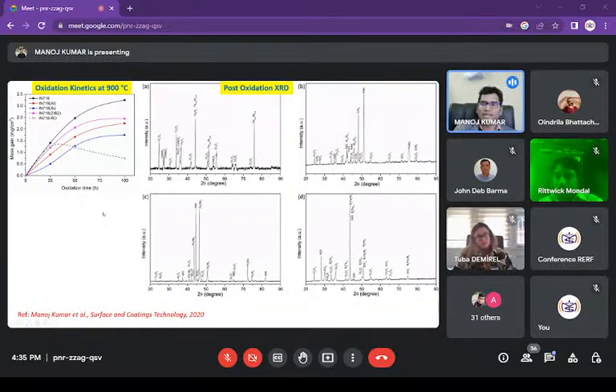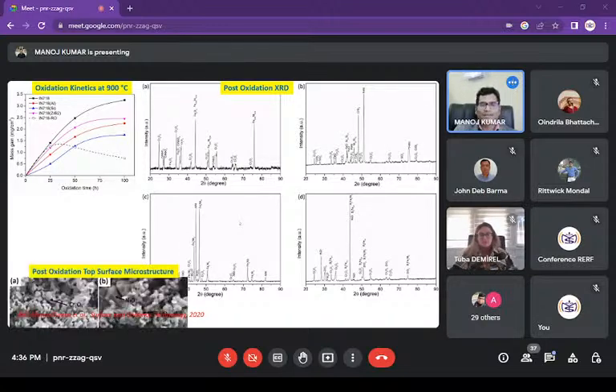And after oxidation, we took out the sample and tried to understand what phases are forming. Why the silicon alloyed surface is not getting highly oxidized is very evident from its XRD profile: many of the silicides, we can see nickel silicides, are still unaffected. They are still stable at 900 degrees Celsius of exposure. That is why they are able to offer oxidation resistance. They are not getting oxidized.